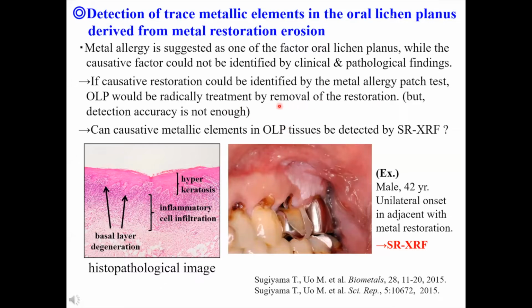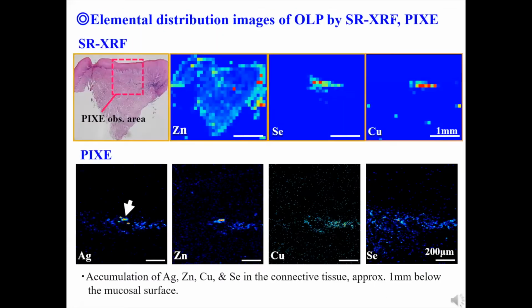However, there are many possible causes, so the diagnosis is not easy. We tried the detection of the eroded metallic elements accumulated in the OLP lesional tissues. This slide shows the typical image of an OLP tissue specimen. From the synchrotron radiation XRF result, characteristic accumulations of selenium and copper were revealed. This facility is not optimized for heavy element detection. Therefore, another method, micro-PIXE, is also combined.